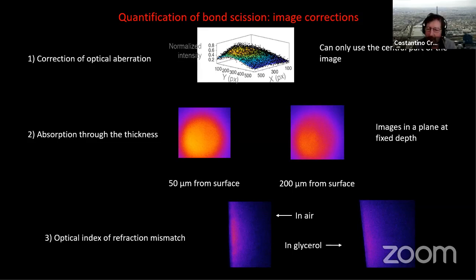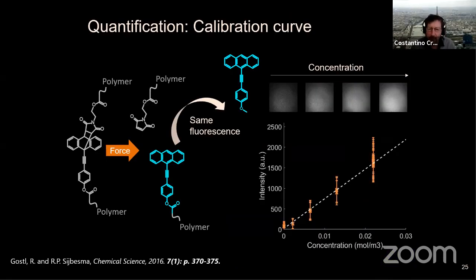Now, you still would need to calibrate that with the number of molecules. The next step, and this comes from our chemist friends, is that it's possible to synthesize this molecule on top, which looks very much like the broken fragment that you have in the real material. This molecule is soluble in the polymer, so you can solubilize it at different concentrations and then measure the intensity. If you measure the intensity as a function of concentration, there is a pretty good linear regime. If you continue higher, at some point there is a plateau, but there is a nice region of about a factor of 20 where you have a linear regime, and you can use that to calibrate your data, if you put the right kind of molecule in the sample.